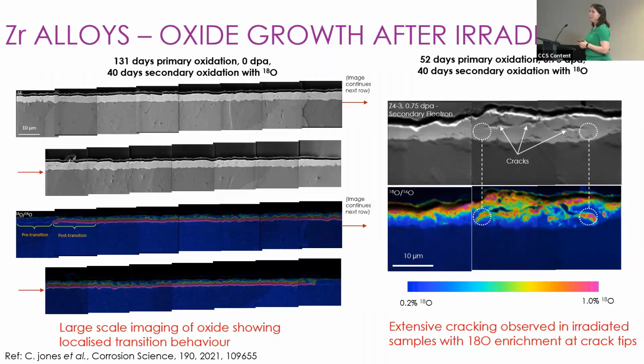And what became immediately apparent is that although zirconium undergoes these transitions, and you can see that in the weight gain behavior of these zirconium alloys, people thought that maybe the whole alloy transitions at the same point. But what we can show with the NanoSIMS and with these oxygen-18 labels is that things do not always happen at the same time. So where we have incorporation of oxygen-18, which is this pink line along here, the metal oxide interface, that is oxide that has grown in those 40 days that the oxygen-18 label was present in the autoclave. So you can see here that the outer oxide of this region must be completely porous to the water. The water is able to penetrate through that oxide and react directly with the metal underneath. And so this has gone through a transition.